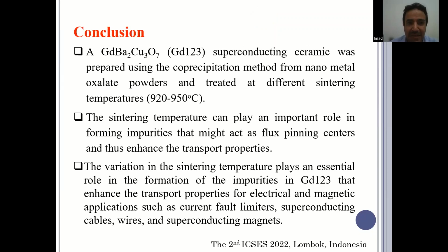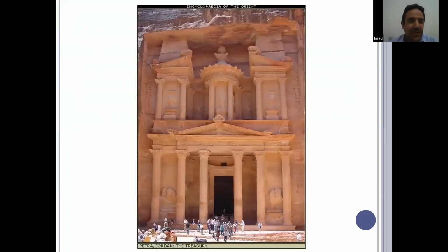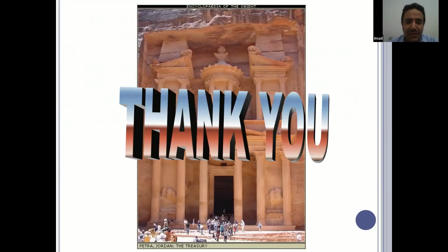I can now say in the conclusion that we succeeded in producing superconducting material, type GD123, using the co-precipitation method with metal oxalate powders as a starting precursor. The sintering temperature plays an important role in forming impurities that might act as flux pinning centers and thus enhance the transport properties. The variation in sintering temperatures plays an important role in the formation of the impurities, and that enhances the transport properties for electrical and magnetic applications such as current fault limiters, superconducting cables, wires, and superconducting magnets. With that, I end my presentation. Thank you for your attention.